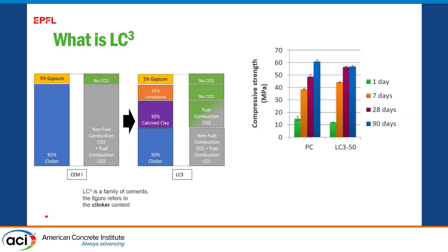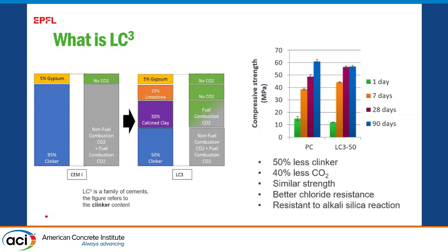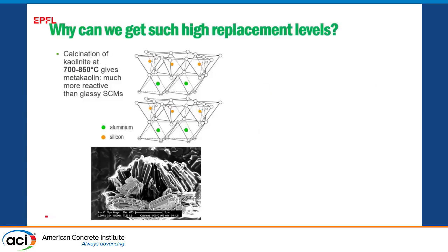Fly ash is maybe catching up at some time after 28 days. You can't get the same early strength, and that's often a limitation on the substitution level for practical construction. So just to summarize briefly, we've got 50% less clinker, 40% less CO2, similar strength, and some properties like resistance to chloride and alkali silica reaction are very much improved.